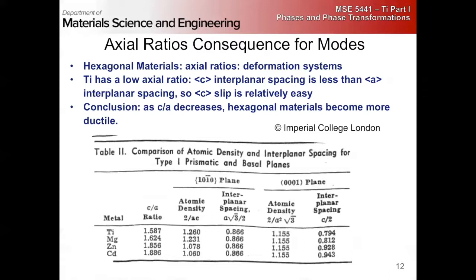If that were the case, I mean, if this were a hundred percent true, that would mean that omega titanium would be super ductile, because its c over a ratio being simple hexagonal is much less, c is much less than a. And in fact, prismatic c is the slip, the easiest slip mode, but it still has a resolved shear stress on the order of gigapascal plus. So it's very brittle. So this doesn't hold as a hard, fast rule.